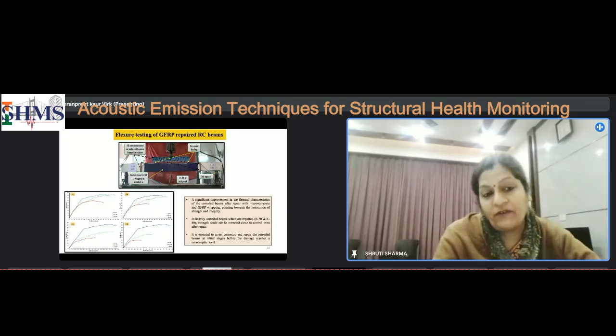But when we saw the 30 day and 40 day samples, we felt that if you see the green curve, there's a huge gap between blue and green. Red is of course the damaged, corroded one. We are not able to restore the strength when the sample is badly damaged.